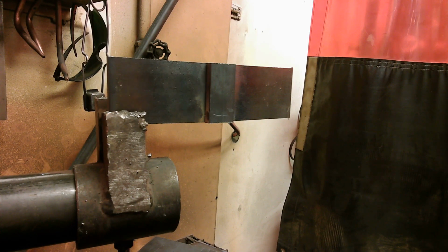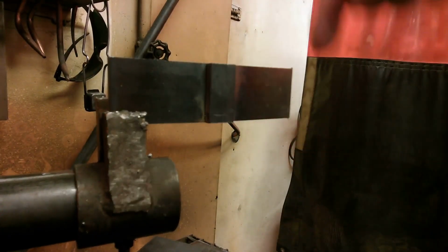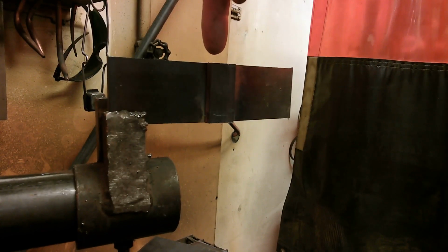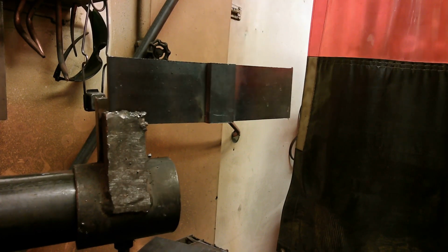Okay, so I'm set up for cutting off the backing strip. This is typically how I do them. I'll stand the pieces up on edge. We've got the 1/4 inch by 1 inch backing strip here. And I'm simply going to take an oxyacetylene torch, starting at this corner, and cut all the way across. I've done this with plasma before. The problem with plasma is it'll jump an air gap and it'll gouge in your part with very little effort. So it's faster, but typically you end up ruining more bend tests than it's worthwhile.